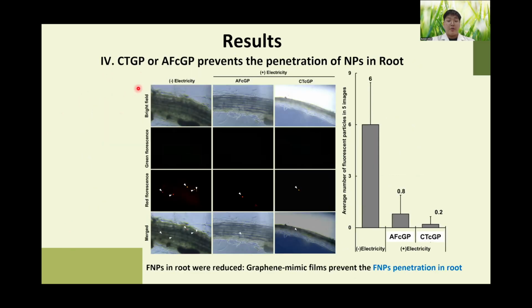Finally, I investigated whether the electrically supplied film could suppress the penetration of the nanoplastics into crops. The number of nanoplastics in the roots was significantly reduced by the CTcGP or AFcGP supplied with electricity. Therefore, I showed that the films can effectively prevent nanoplastic penetration into crops.